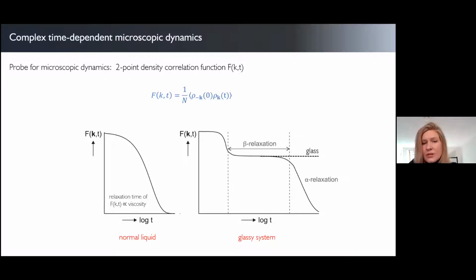And this plateau here is then actually an indication of solid-like behavior, because if this function remains finite, it means that the particles retain strong correlation with their position a long time ago. So that's indicative of solid-like behavior. Now, if you wait long enough and you're still on the liquid side of the transition, this function will decay to 0 eventually. But if you're in the glass phase, then this function will remain finite for as long as you can do the experiment. And that is, in fact, also an order parameter for the glass transition. So whether the long time limit of this object becomes 0 or remains finite.